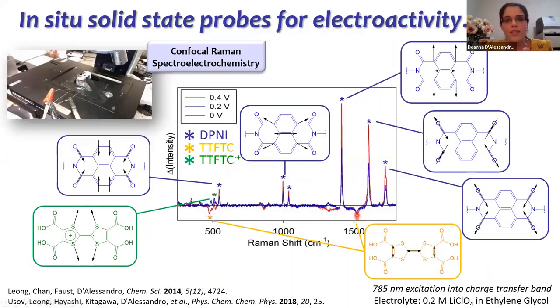So really wanting to understand more about the intimate effects of electroactivity on these materials, here is a confocal Raman spectroelectrochemical method where we use a screen printed electrode, and the metal organic framework here sits on the working electrode, and we bead a drop of electrolyte to complete the electrochemical cell. Without wanting to labour this too much, what we essentially see in applying potential here is a change in the vibrational frequencies for the TTF and naphthalene diimide that are consistent with the change in their redox state.